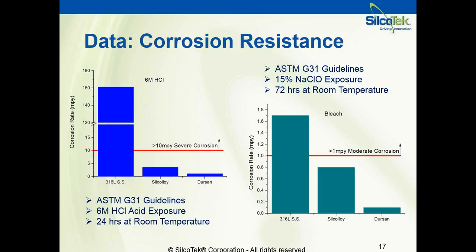On the right, you'll see that we did the same test with bleach, and you may be wondering, now bleach, that's an odd media to evaluate, but with the presence of the oxides and the HCl in bleach, it can actually simulate the introduction of moisture into a semiconductor manufacturing process. So we thought it would be important to look at. So we did this one in 15% bleach and 72 hours of room temperature exposure.